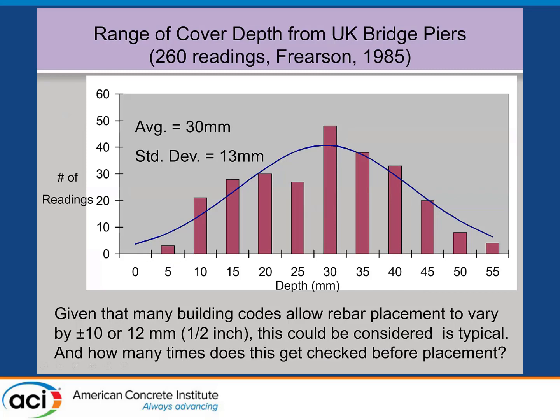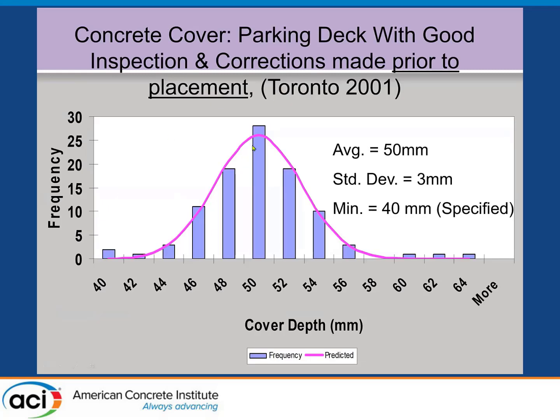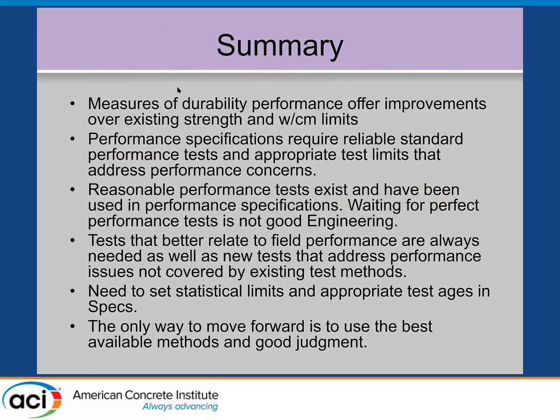We did a parking garage in Toronto at the airport, and the engineer made the contractor check the cover required before each placement in the parking garage, very large garage. They were looking for a minimum of 40 millimeters, which is just over an inch and a half, but they ended up with an average of 50, or 2 inches, and the standard deviation was only 1/8 of an inch because they measured it before they placed the concrete. And so the uniformity in terms of corrosion resistance is going to be greatly enhanced because there aren't any of these bad ones. So we need to measure performance.